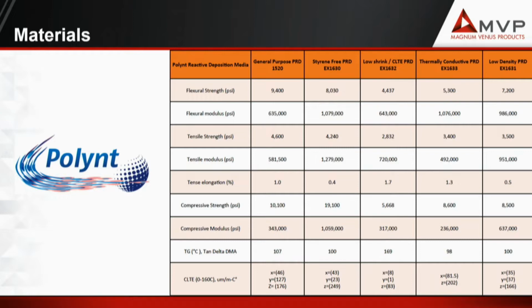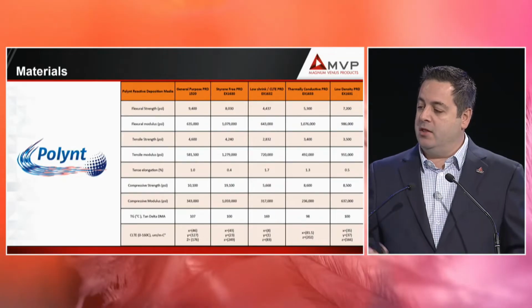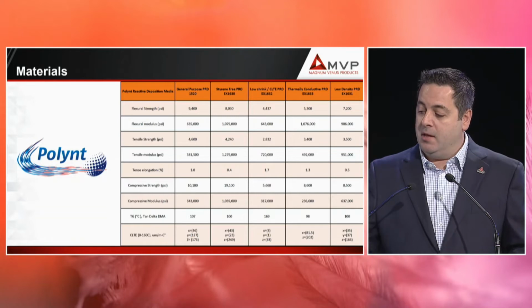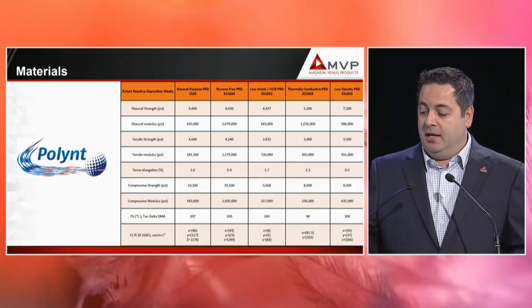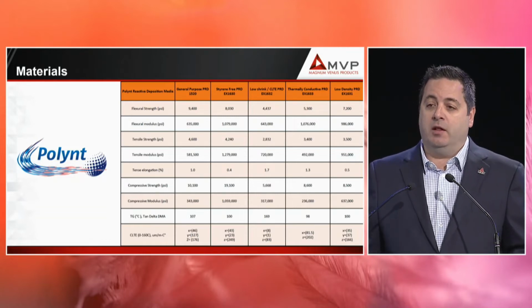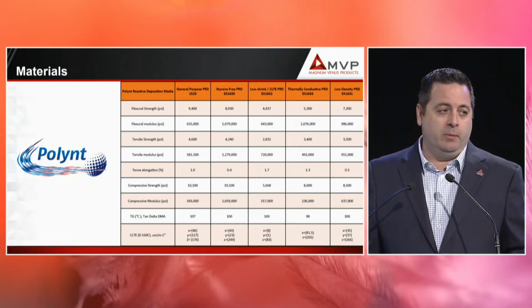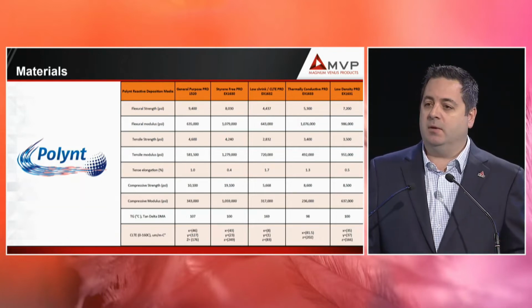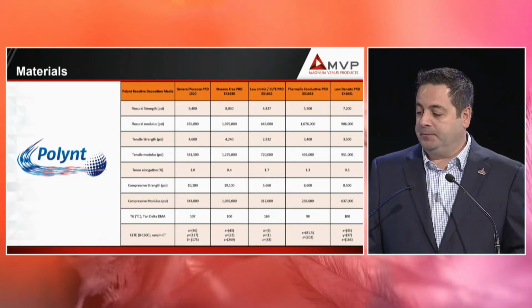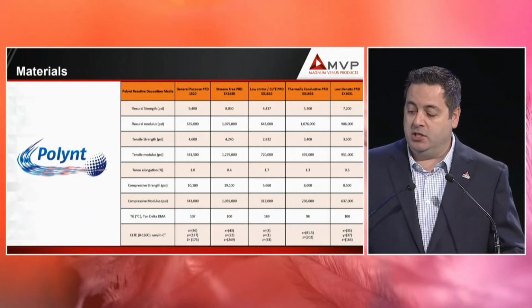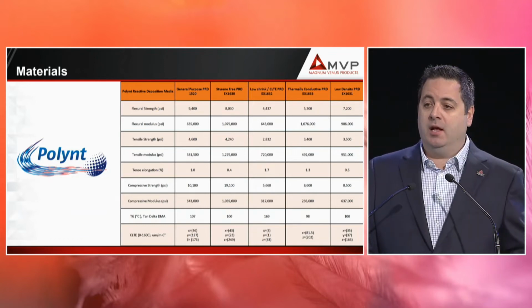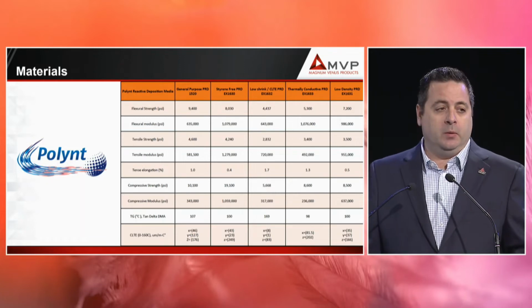But what's really exciting is in the middle section there, the middle material, you can see on the bottom the CLTE is very, very small, and this is approaching aluminum in the sense of the expansion rates that you're seeing in tooling, as well as the Tg, the temperatures at which you can produce to. So we're at the low end of autoclave tooling and have plans to be into full aerospace autoclave tooling with the pressures.